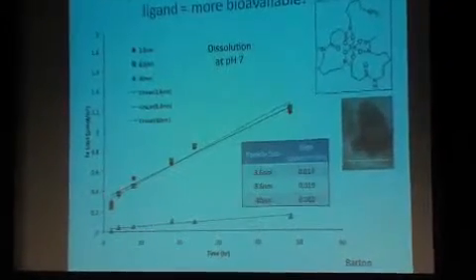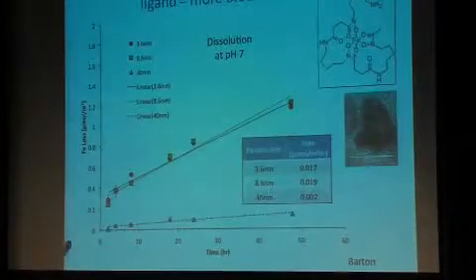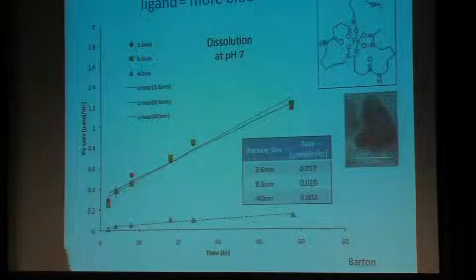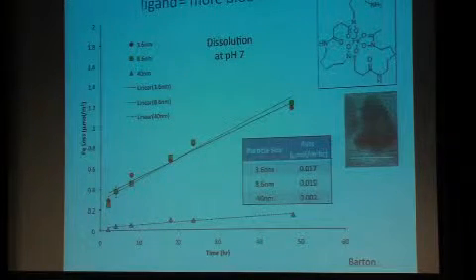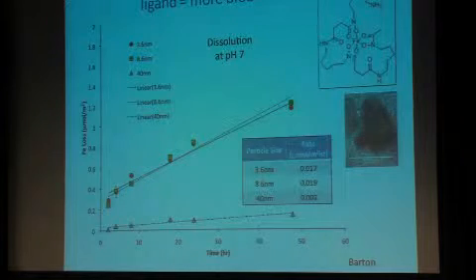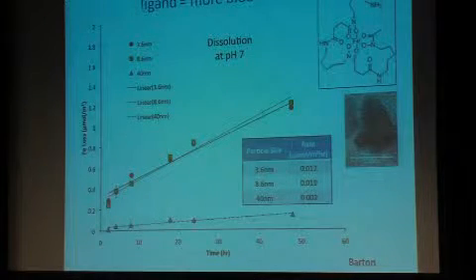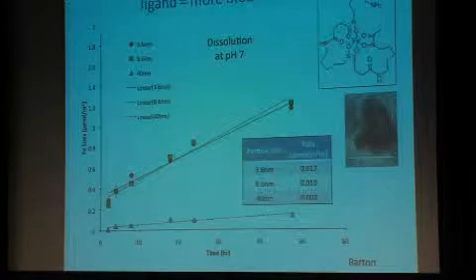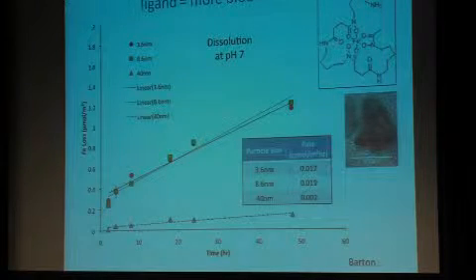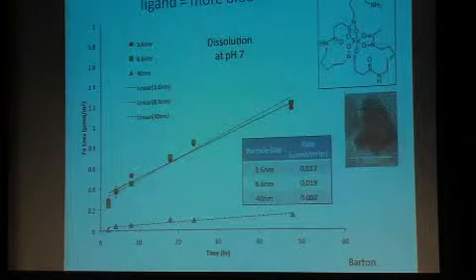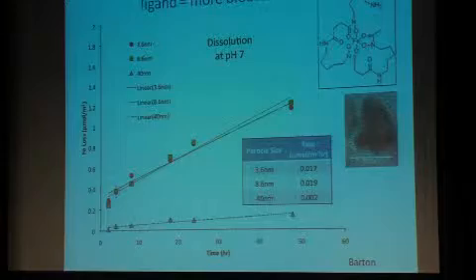For the larger particle, the rate is about an order of magnitude slower than these little nanoparticles. So this different reactivity really plays out. They dissolve about an order of magnitude faster. Now that's important that when we did this experiment, we did the experiment with the same amount of surface area per particle.